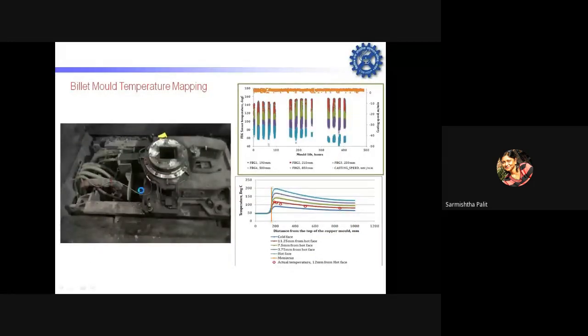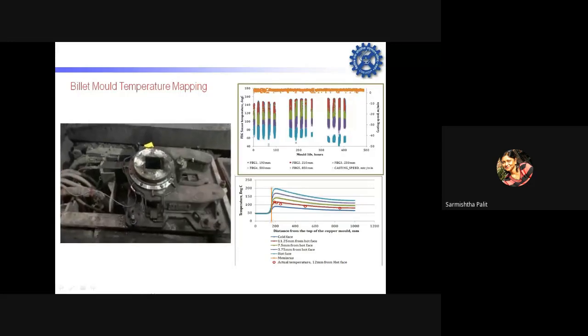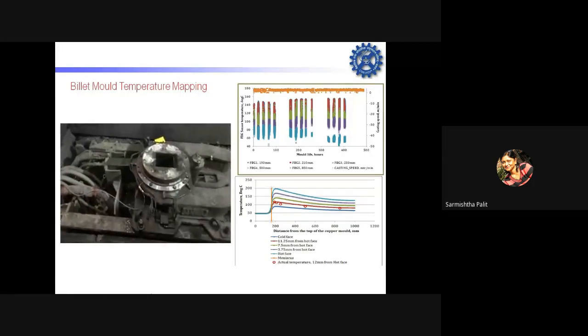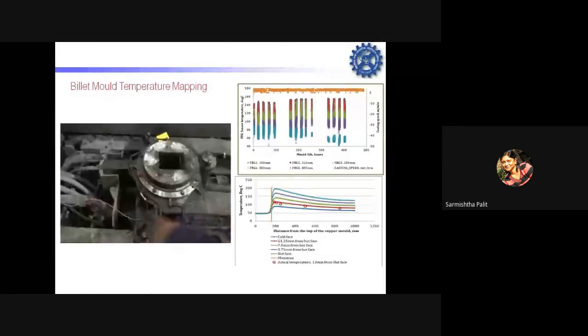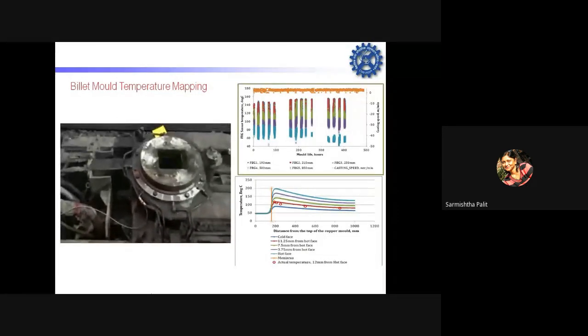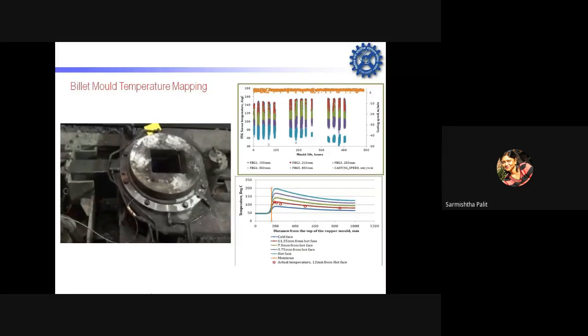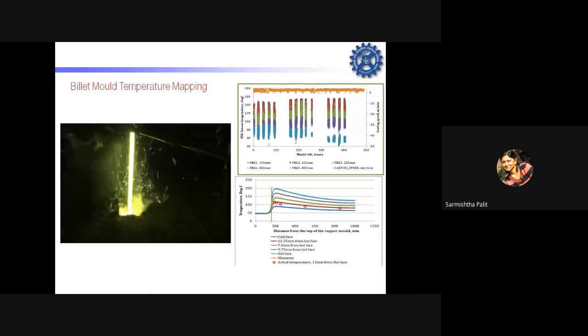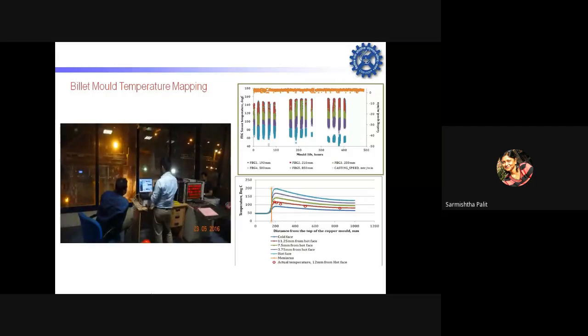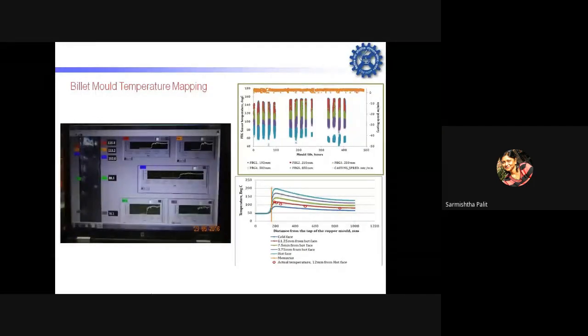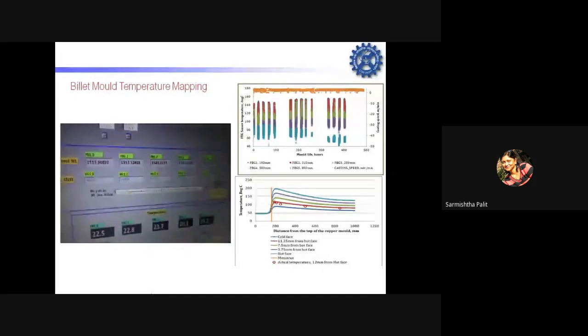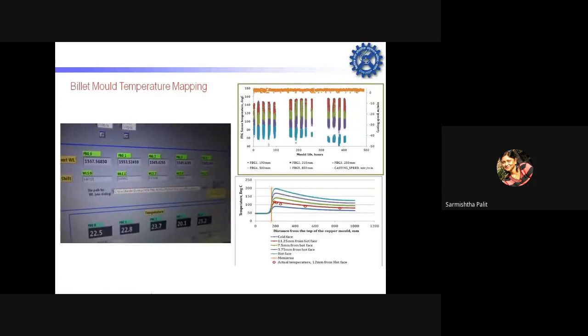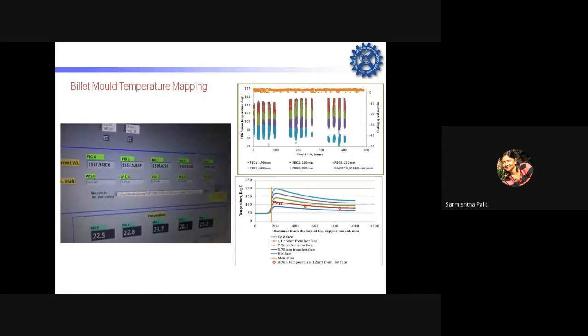Chandan, click on the video. This is at the caster, and the square face on the top is the top of the billet, and only a single billet is coming out. You see how liquid metal falls into this mold. Can you imagine if there is any leakage? Liquid metal at 1200 to 1800 degrees, if it comes together with water, what will happen? It will be an explosion. And all these results you are getting in the control room.